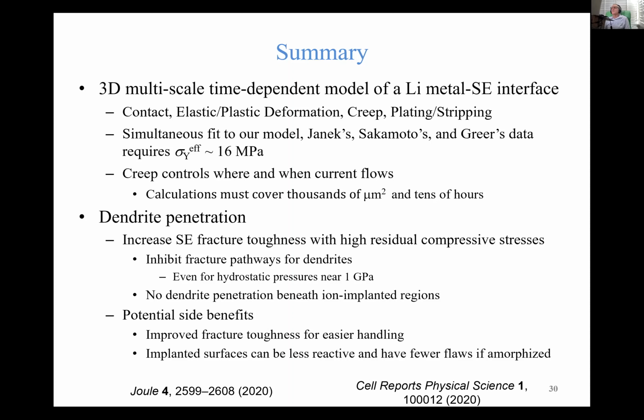And what we found is that we can get a simultaneous fit to our model and to Janek's data, Sakamoto's data, and Greer's data if we assign an effective yield strength of close to 16 megapascals for the lithium. The main learning we got is that it's really creep that controls when and where current flows. So if you have contact at a particular point, that's where the current is flowing. And 5 hours later and 30 microns away, the lithium may have flowed into a new place, and now you have a new contact, and that's where the current is going to flow.